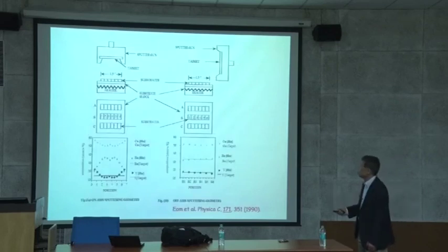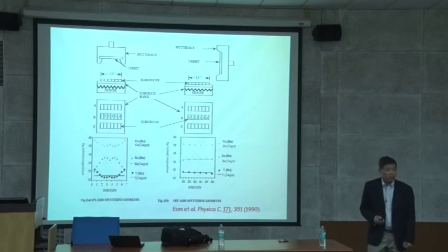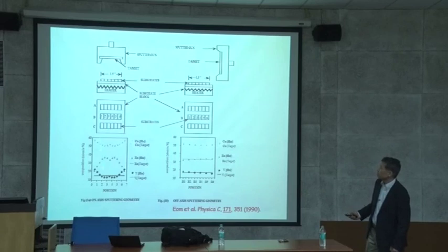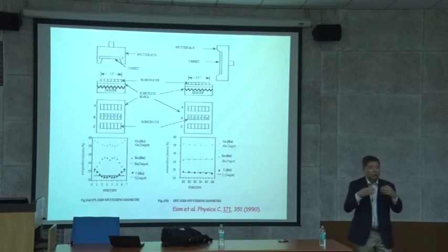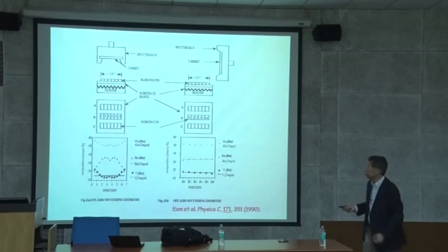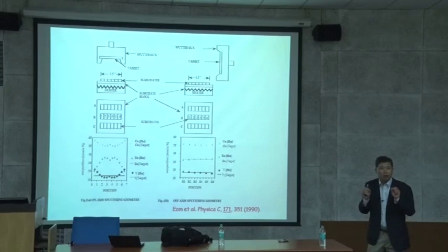Let me introduce the distinct difference between on-axis sputtering and off-axis sputtering. When you do on-axis sputtering and look at the composition of yttrium, barium, copper across the sample, the uniformity is terrible in certain regions. The reason is that the particles coming from the target's erosion area form a ring pattern, and those regions have the highest negative ion flux. Whenever you hit the region with the highest negative ions, you get the most serious negative ion bombardment. So the non-uniformity comes from which regions have more negative ions.